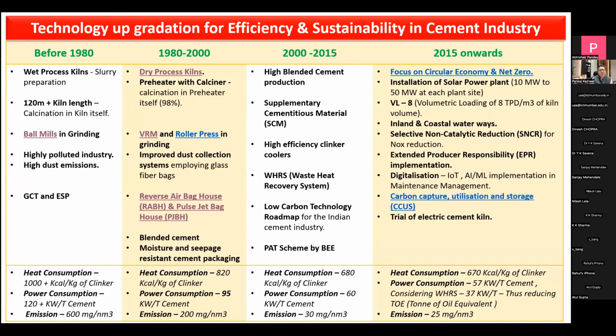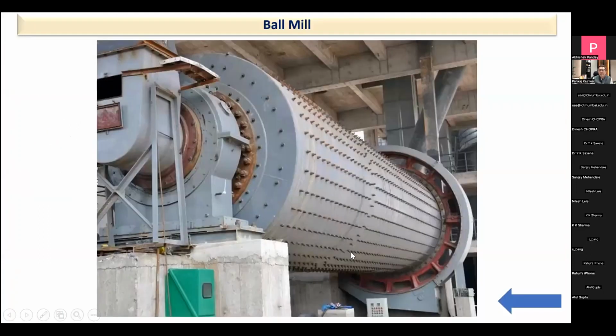As we can see, before 1980, earlier we were using the wet process kilns, where we had to prepare slurry for the raw material. And we were using ball mills at that time. Ball mills, as we understand, have huge grinding media inside, which is dead mass that has to be rotated along with the raw material. So this was a huge energy guzzler. The main energy consumption in the cement plant is in these mills.